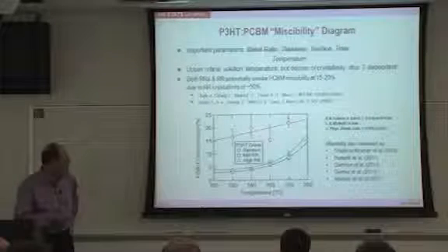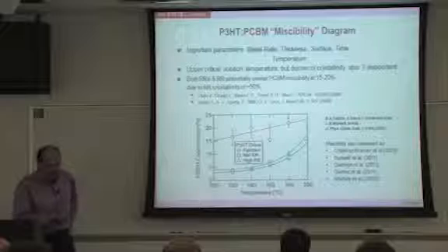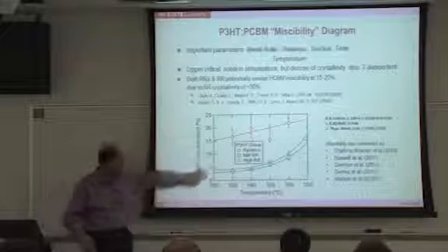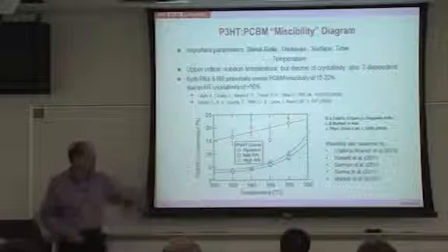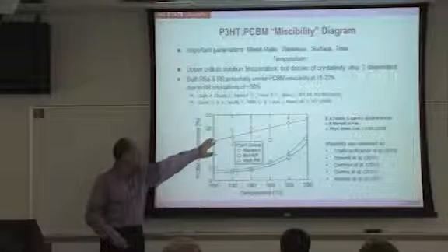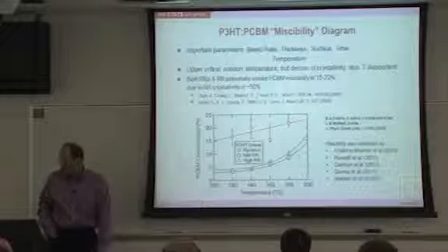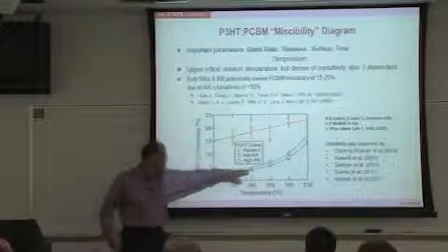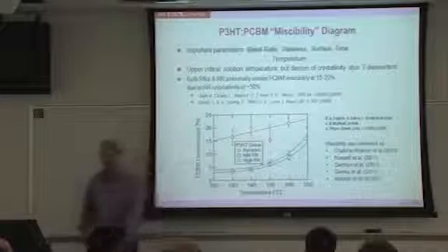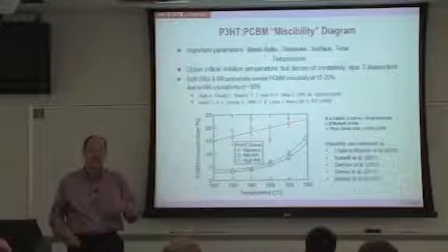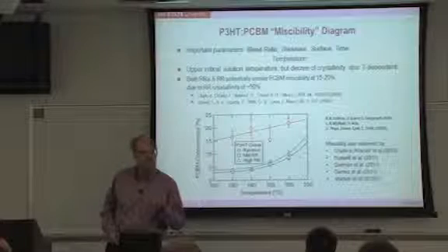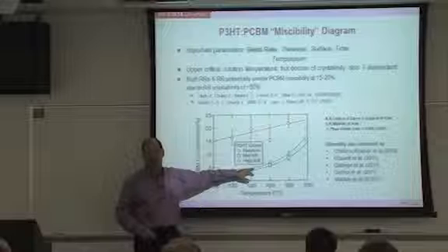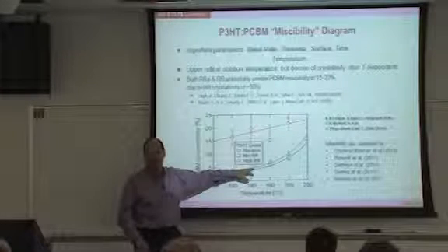And so there seems to be, and that degree of crystallinity has some temperature dependence. So we have to be careful how we interpret this. But you see that these can be fairly large in regio-random. These are sort of up to 15–20%. In the regio-regular, it's more on the order of 5% at typical annealing temperatures. But that still means if I have 50% crystallinity, that I have 20% PCBM in the amorphous phase.